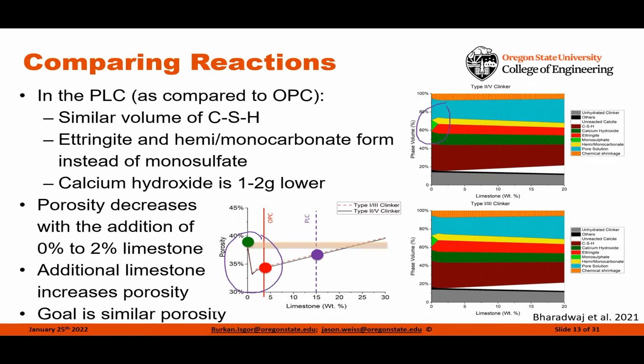So all of a sudden, we're starting to replace some of the monosulfate with things like ettringite or monocarbonate or hemicarbonate. And we're starting to be able to describe the reductions in porosities that are occurring in those systems. And then that reduction in porosity translates over to a change in strength or a change in transport properties. So this has been very useful in explaining to people what's happening in these PLC systems.